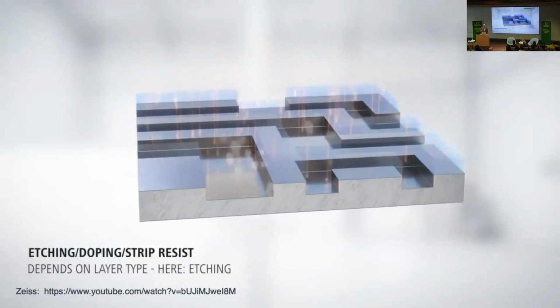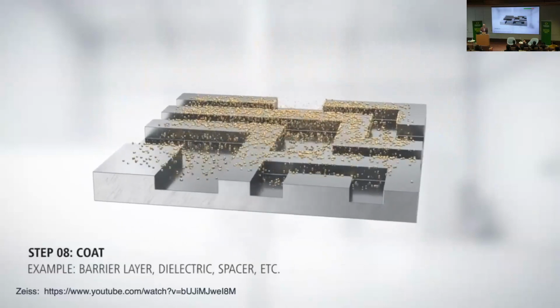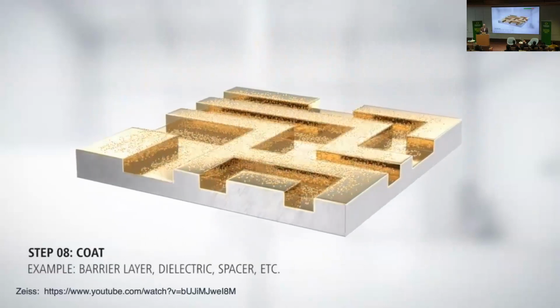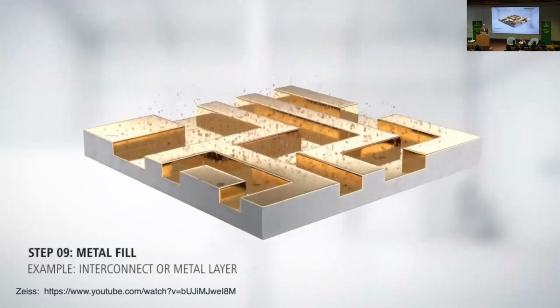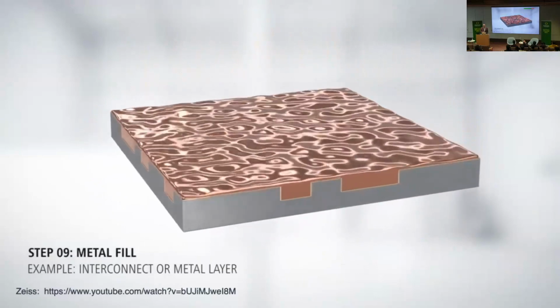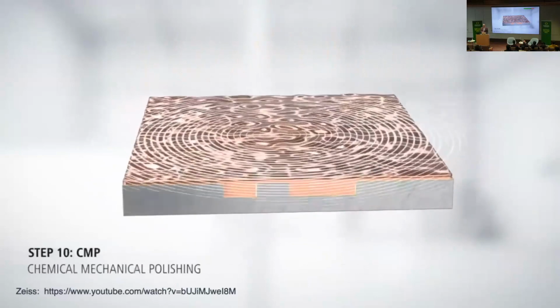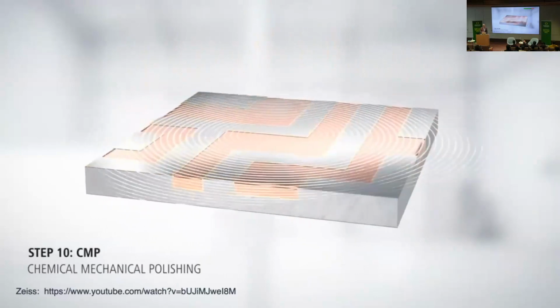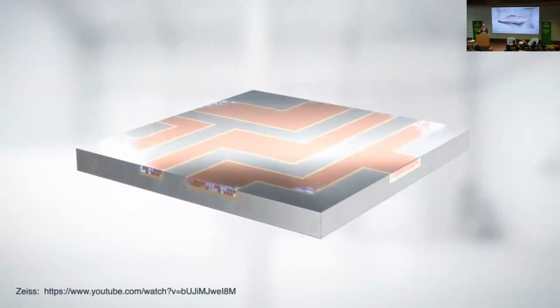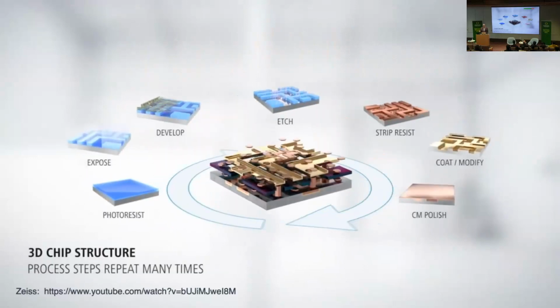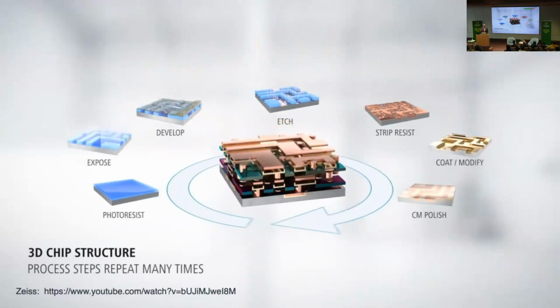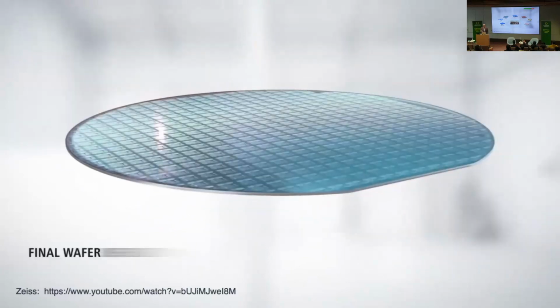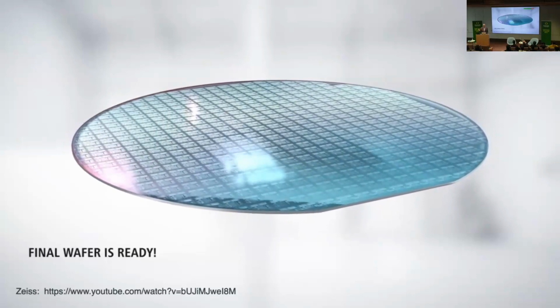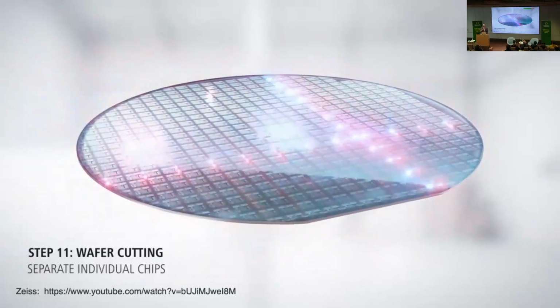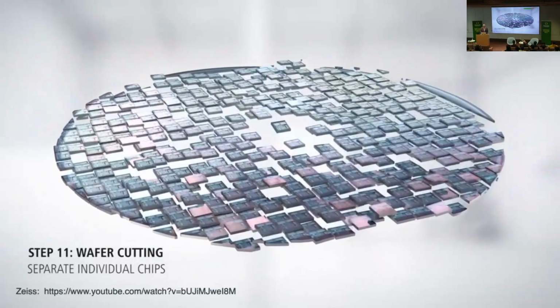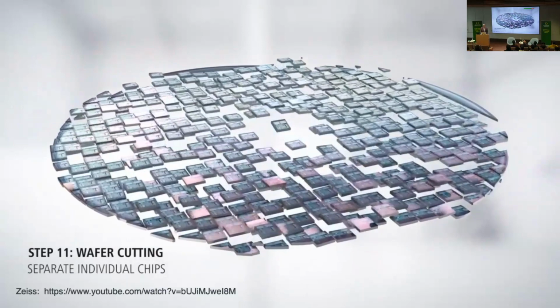Then you can take that polymer and expose it to usually some sort of oxygen plasma to transfer that pattern from the polymer into the silicon. Then you treat the silicon with different barrier layers and start filling it up with metal. Often you overfill with metal, so you have to polish it back. That's how you make a single layer of metal pattern on a wafer. You do this over and over again and build up a complicated device. That's the microelectronics process in about 45 seconds. Then you cut up the wafer and have all these individual chips. This is driving most of the world's economies today, right?